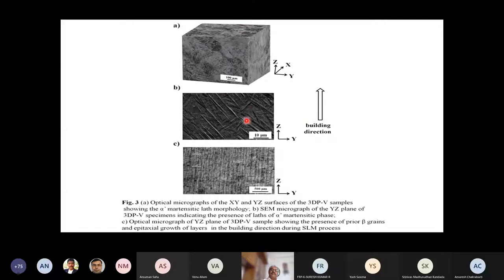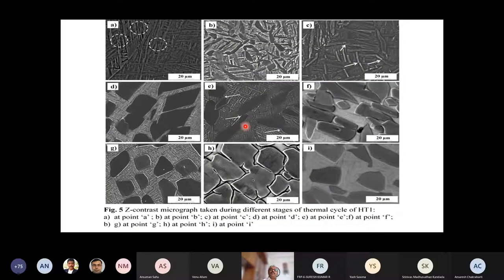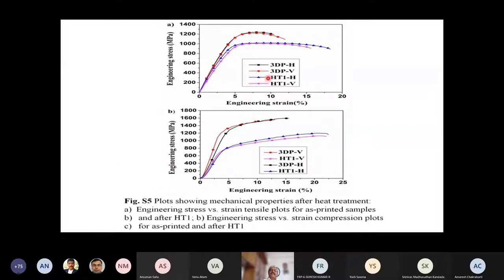So this was the initial material that we got after deposition. And by designing this specific heat treatment, this most undesirable microstructure we could transform to this kind of microstructure or this kind of microstructure for different conditions. So these are among the most suitable and desired ones. And this had a significant effect on properties also.